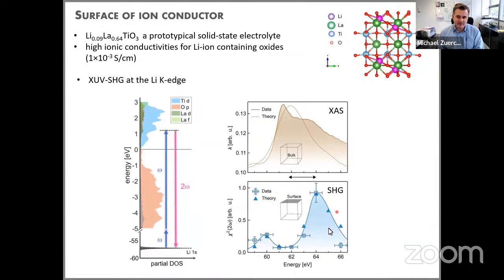Now the interesting thing is that we can compare this to second harmonic generation. These measurements were done at the free electron laser on this very same sample. First of all, it looks quite different. That's good, because there's an expectation that there should be a change between bulk and surface. We see a structure with two humps, and some energetic shift of the main resonance. The other thing is our theory got better in the last year or two. We can now very nicely predict the second harmonic response of the system as well, and analyze these shifts.